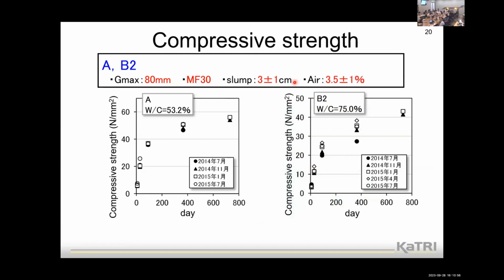This slide shows the long-term compressive strength development of dam concrete. I know almost all of you research fresh concrete, as you know. This shows mixes A and B2. These concretes are the same in maximum size of gravel, type of cement, slump, and air content. These are the same, and only W/C, the water-cement ratio, is changed.